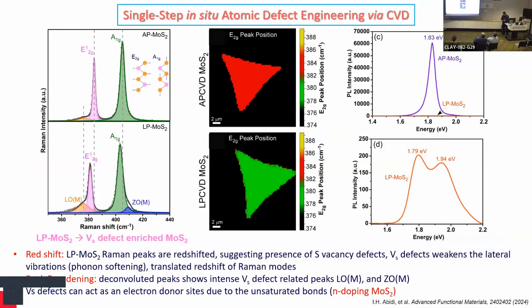Once we do some more characterization to see what these defects can do, especially in terms of photoluminescence emission, you can see one type of growth gives very high photoluminescence, and another gives very low. So for the same single crystal MoS2, in one case the photoluminescence is like 60,000 counts at the same parameters, and the other MoS2 gives like 200. So the photoluminescence is completely gone.